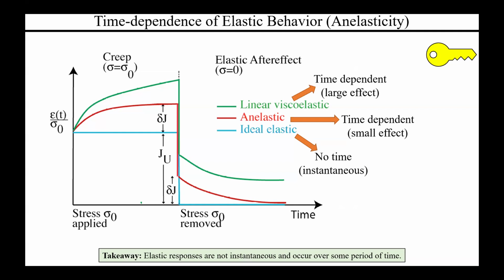So this would be your linear viscoelastic and anelastic. We'll talk about other types of time-dependent behavior, particularly when we get to things like polymers. But if you look at the anelastic case, this is a small effect. So, think of the y-axis here is you've applied an initial stress onto the material. That stress is constant, but you're changing the strain as a function of time. So in the case of the anelastic, you apply that stress, you have this small change in the strain as a function of time, but eventually it plateaus. And then when you remove that stress, it takes a little bit of time to restore all of that strain that was induced. It's not this immediate jump back down to no strain at all.